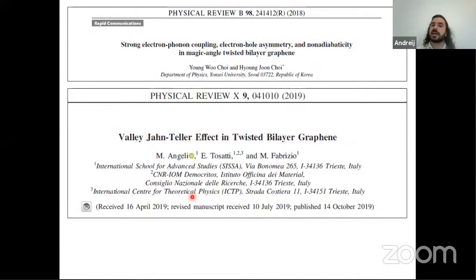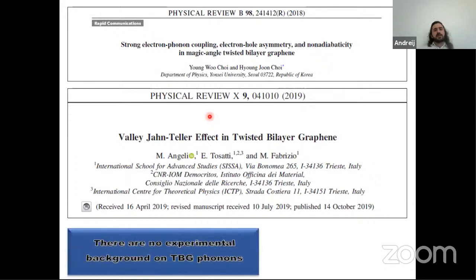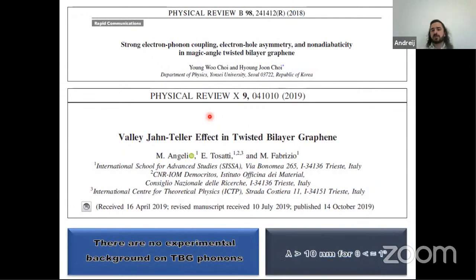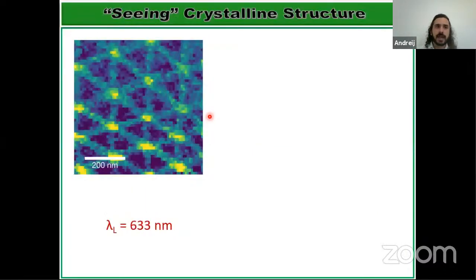Okay, but on the other hand, there is an alternative story. So some theorists show that there is a very strong electron-phonon coupling at the magic angle graphene, and it's so strong that some exotic physics show up, like the Valley Jahn-Teller effect, and this could have some contribution to the superconductivity. However, there is no experimental background on TBG phonons so far, I mean the magic angle TBG. And for angles close to the magic angle or smaller, the lattice constant of the TBG is about 10 nanometers. So it is a nanoscale problem, which only a nanoscope can deal with properly. And now I show one of our first results.